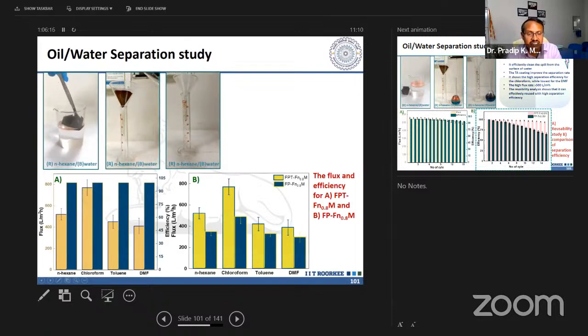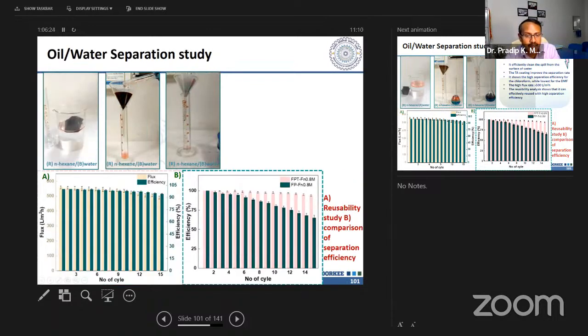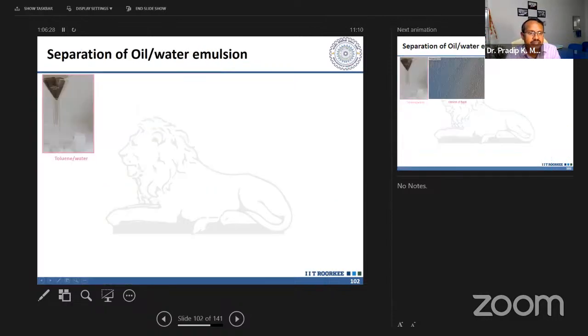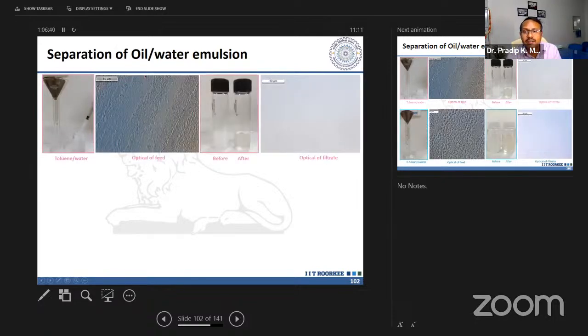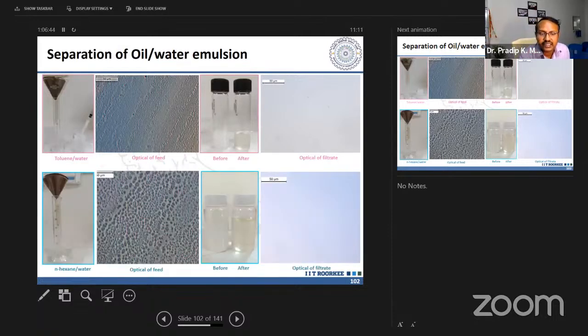Then we have checked the flux. The flux rate is very, very high, almost 500 liters per meter square per hour. And we have also checked the efficiency. Another most important thing is that we made a combination of oil, water plus surfactant to make a colloid, and our system is able to break the colloidal system and separate the oil and water. Here is the optical image of the solution before separating. After separation, there is a very, very small amount of droplet available when I used the colloidal system. You can tell the clarity of the water before and after very clearly.